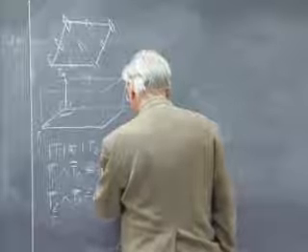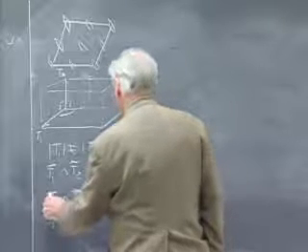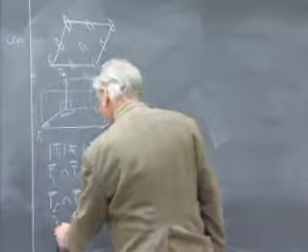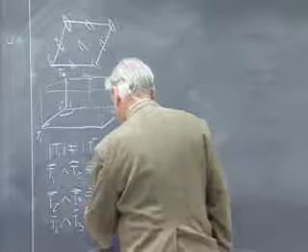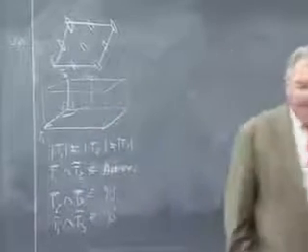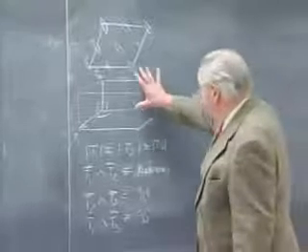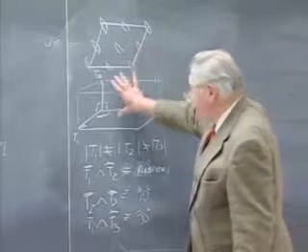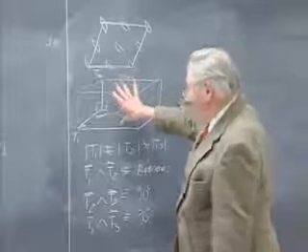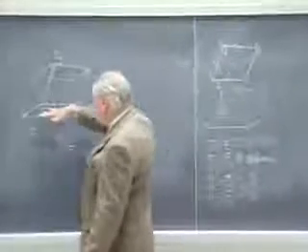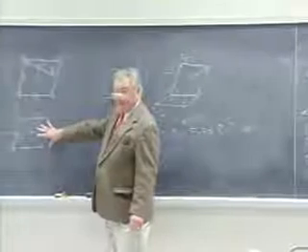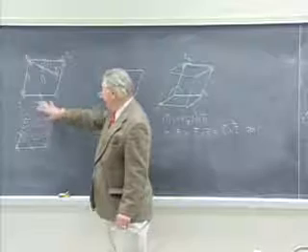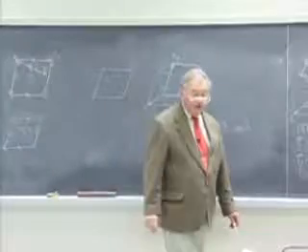So that can be any general angle. T2 and T3, and T1 and T3 want to be exactly 90 degrees. Okay, so we're getting space lattices that have a degree of precise specialization, and the reason is that the geometry of the base of the cell is inseparable from symmetry in the base of the cell that demands the degree of specialization that makes the space lattice unique.